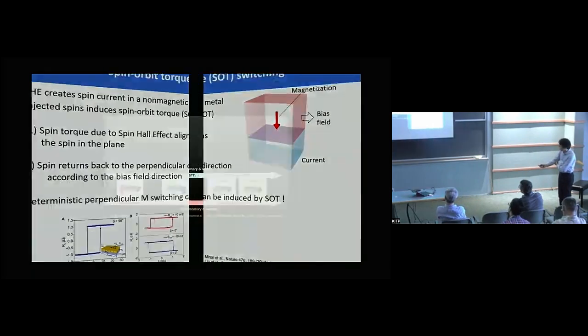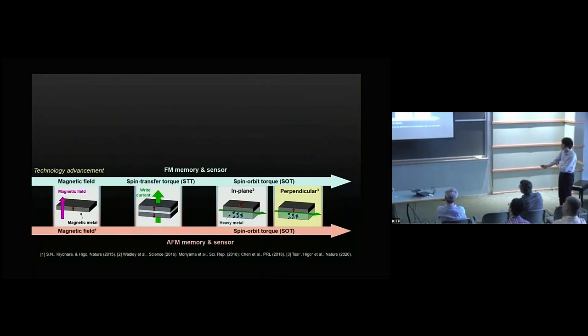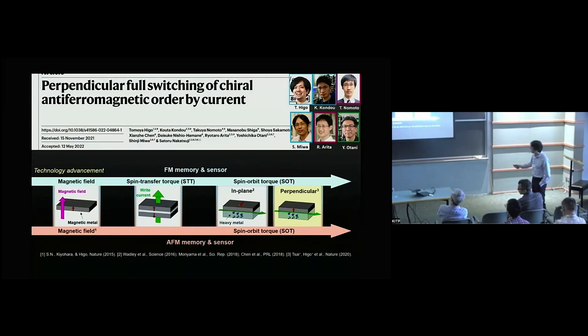So let's see whether this is going to be useful. And this is a kind of roadmap. This has been made for the ferromagnetic spintronics field. Since the 20th century, this has been developing through magnetic field control to STT, spin transfer torque control. Now spin orbit torque control is a major research topic in spintronics. In particular, this perpendicular orientation turned out to be quite useful when you consider how to integrate these memories as densely as possible, because it's consistent with the scaling of these magnetic bits. And so the question is whether this is also possible for antiferromagnetic memory, if you like. This is exactly what we made quite recently, and we found a perpendicular field-free switching.